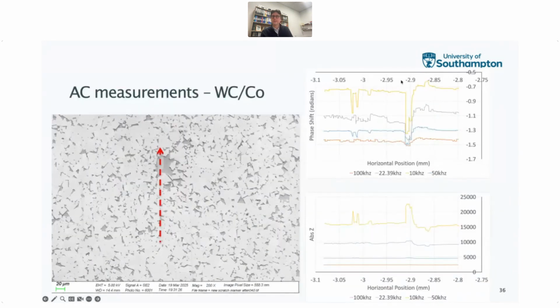And so what we can do then is start picking out those different frequencies that are responding differently and trying to understand whether that's giving us any information. And what we noticed that particularly was getting us negative phase angle shift as we're traversing some of these particles of the cobalt here. You can see this coming out at certain frequencies, a corresponding increase in the absolute value of the impedance, and then a drop when actually we're moving into the cobalt phase.